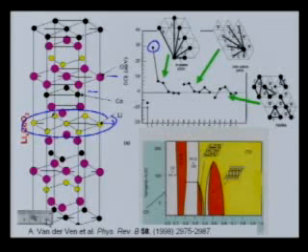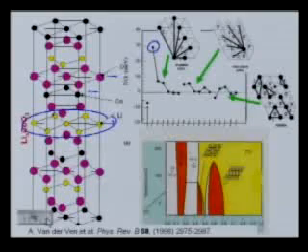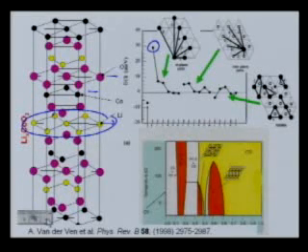And again, let me stress that these ECI are effective interactions. If you look at the first neighbor, it's only 30 millielectron volt. Okay? To give you an idea, those first neighbor distances in the lithium plane are about 3 angstrom. If you evaluated the electrostatics of a +1 charge and a +1 charge over 3 angstrom, you'd get something that's close to an electron volt.